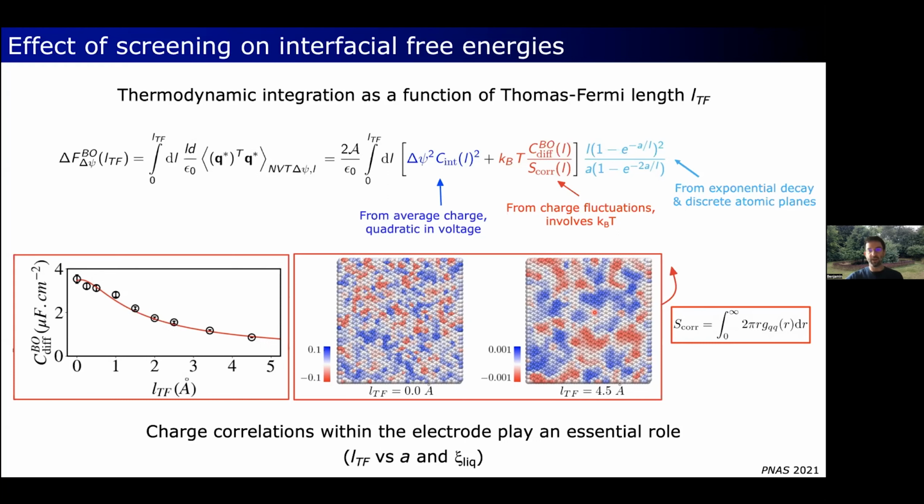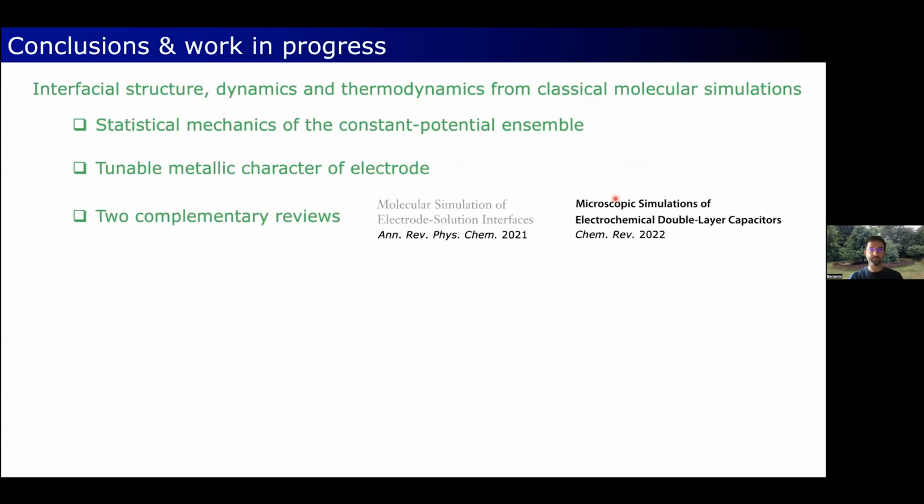And this in turn affects the interfacial thermodynamics, and especially it depends on the Thomas-Fermi length versus the distance between planes and the correlation length inside the liquid. The distance between planes also enters in the expression here, but I'm not going to describe that in detail.